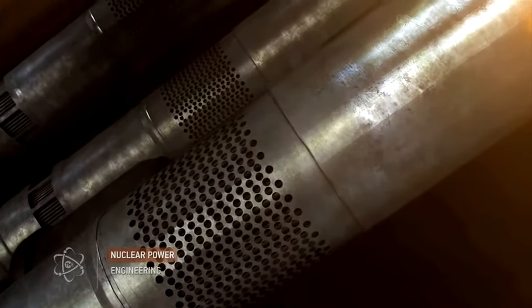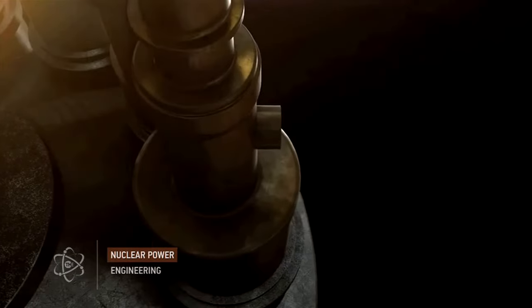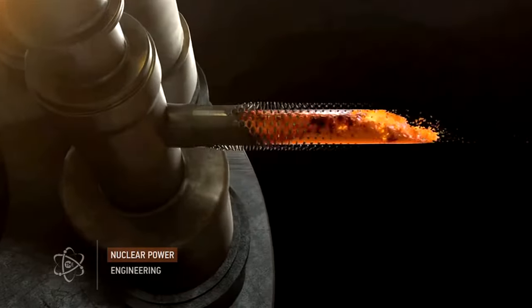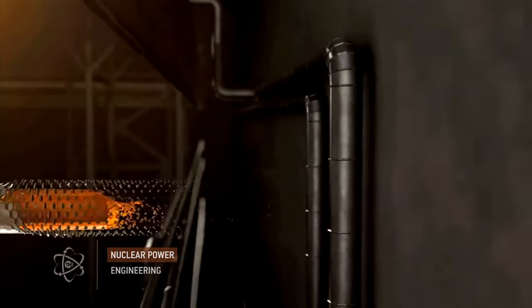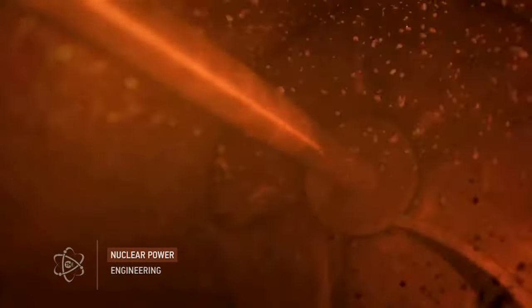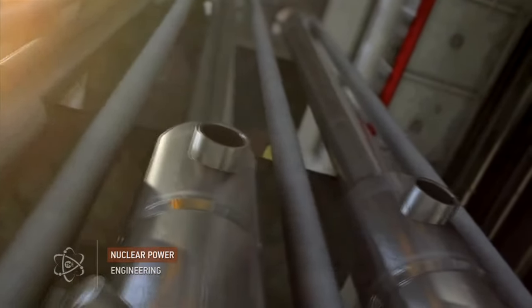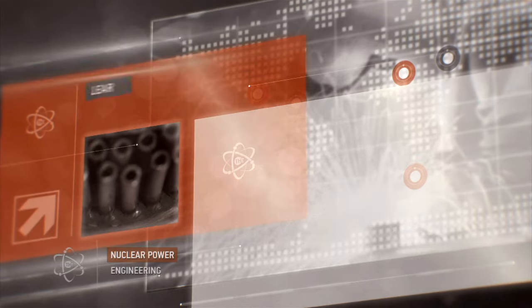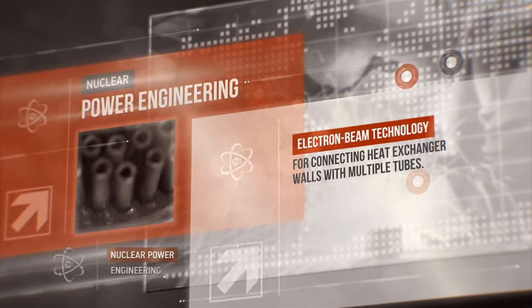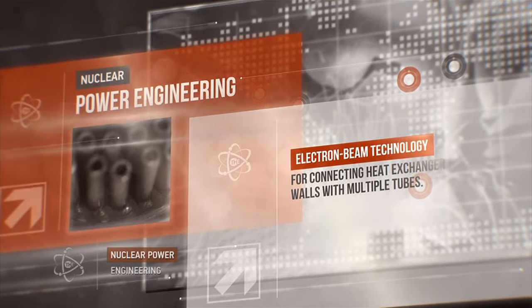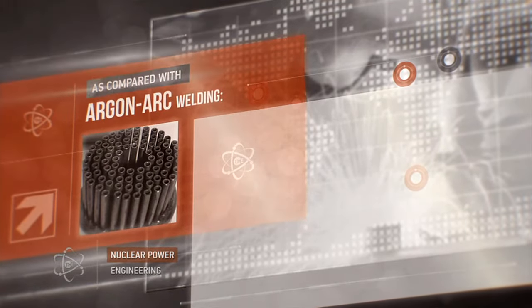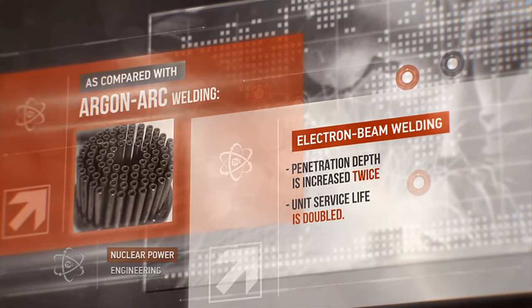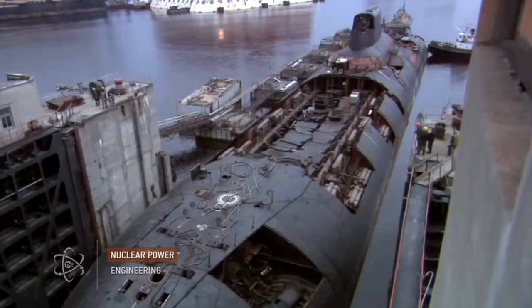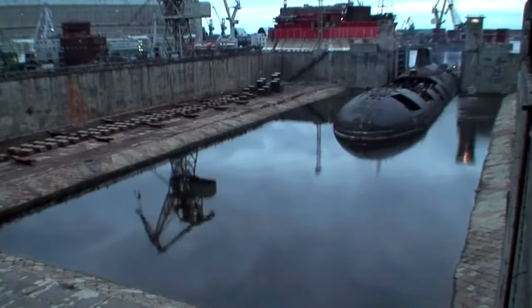A heat exchange unit is the key element of a nuclear reactor. Because of colossal pressure in the tubes reaching 10 megapascals, water does not boil at 270 degrees centigrade. High radiation adds to the most extreme wear conditions. The B.E.Paton Institute has developed an electron-beam welding method to connect the heat exchanger walls with multiple tubes. Unlike traditional argon arc welding, this method doubles the penetration depth and the unit's service life. The welding proceeds automatically according to a preset program. This method has been successfully applied in the construction of nuclear-powered vessels.